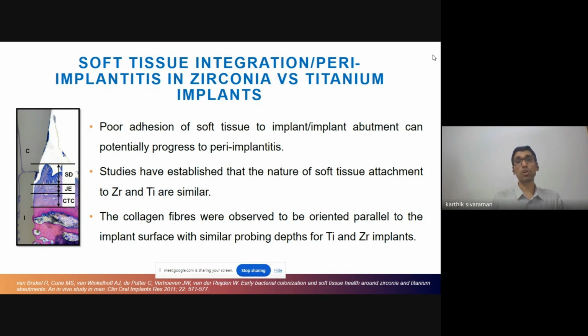And apart from the health, it also plays an important role in aesthetics. It's about the type of margin which is given, the position of the papilla, the health of the soft tissues. They all play an important role along with the restoration to give the final aesthetics. So how do zirconia and titanium compare in this aspect? What is the nature of soft tissue attachment here? So studies have established that the nature of soft tissue attachment is quite similar in both zirconia and titanium. The collagen fibers were also observed to be oriented parallel to the implant surface with similar probing depths for titanium and zirconia implants.